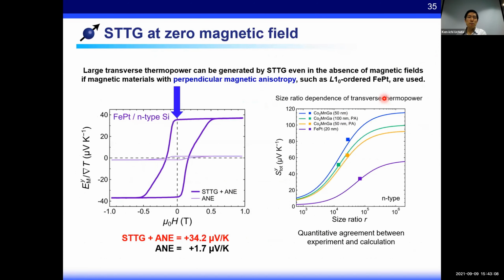The large STTG thermal power can be generated even in the absence of the magnetic field if magnetic material with finite remanent magnetization and finite coercive force are used. We demonstrated this feature by using L10-type iron platinum thin film with perpendicular magnetic anisotropy. In this study, we demonstrated the concept of the STTG using several typical materials. However, there is plenty of scope for performance improvement based on the vast amount of studies on the Seebeck and anomalous Hall effect. Although we focused on the transverse thermal power, the thermoelectric voltage in this experiment, our calculation also showed that the figure of merit can also be improved by the STTG.